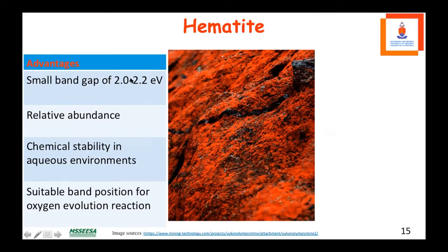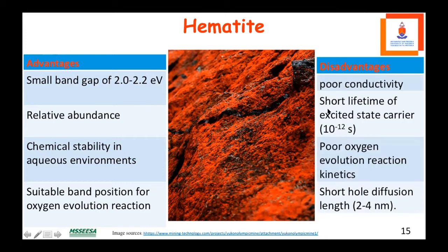It has a small band gap. It is very abundant. It's chemically stable in water and solutions. It has a suitable band gap position for oxygen evolution reaction. But some disadvantages about this is that you have never seen rust being a conductor of electricity. So it has got a poor conductivity. It has got a short lifetime of excited state carriers. It has got poor oxygen evolution reaction, and it has got short diffusion length. So what we need to do in research is to correct these disadvantages.